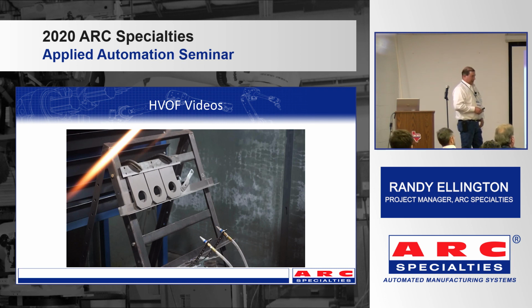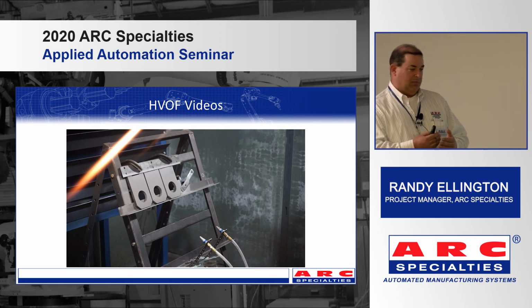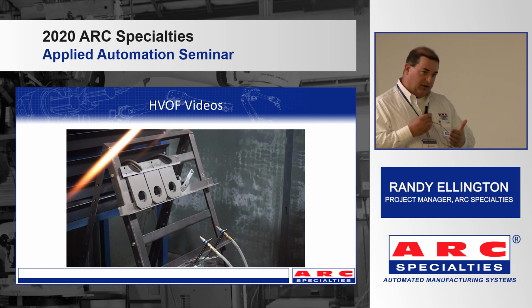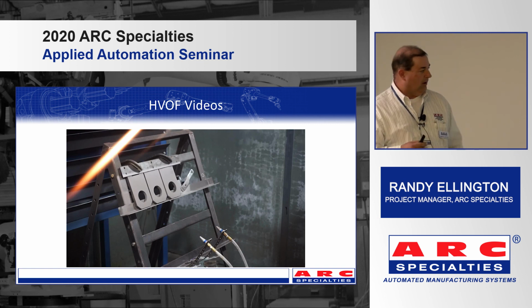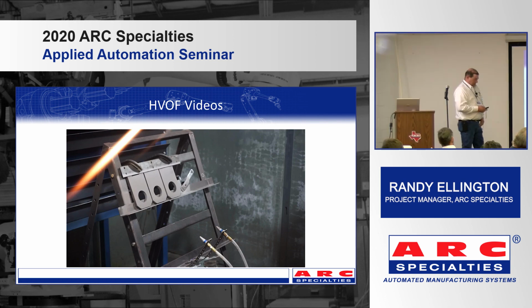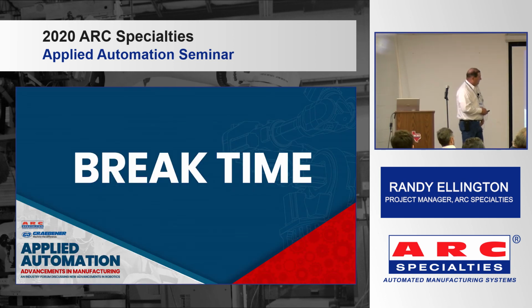So to get 10 thousandths, I've got to put 12 to 13 on. Now with the robot, I can hold that flatness across that part within a thousandth and a half. But with the coating, the first couple of thousandths is what we refer to as just kind of fuzz. It doesn't have all the other splats coming down on it to make it dense and increase the hardness. So the first couple of thousandths are kind of fluff. You've got to take that off and then get down to the good. And I think that should be it.